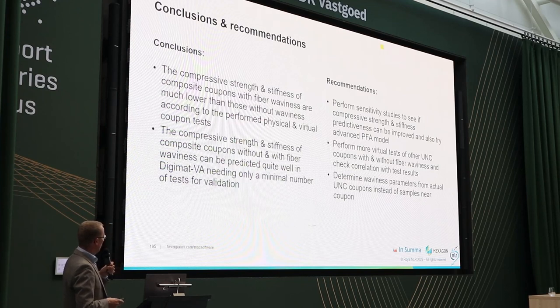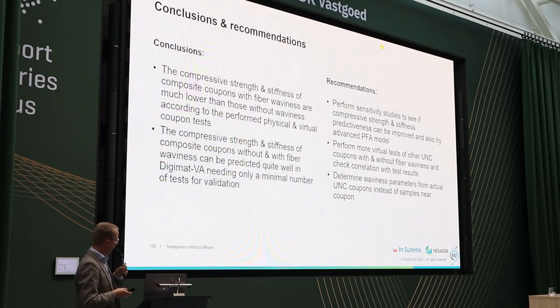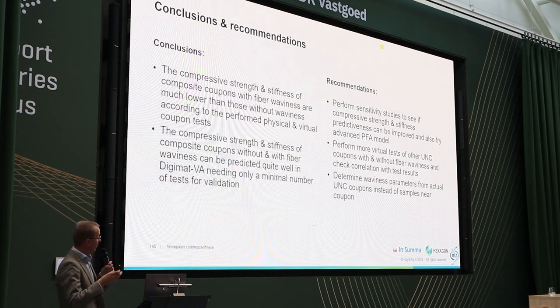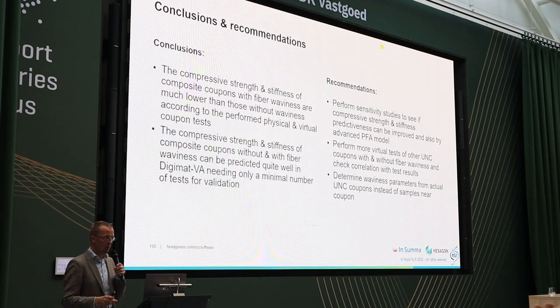Also, simulate some more coupons from each test series. I only simulated one coupon, but I think I should check more coupons to see if it's still that predictive or not. And maybe if I do a similar project in the future, use, for example, CT data and determine the waviness from that. Now I did it from a sample cut beside the coupon, but in the actual coupon the waviness can be a bit different.